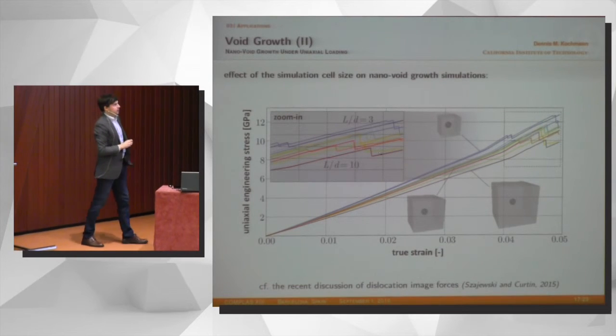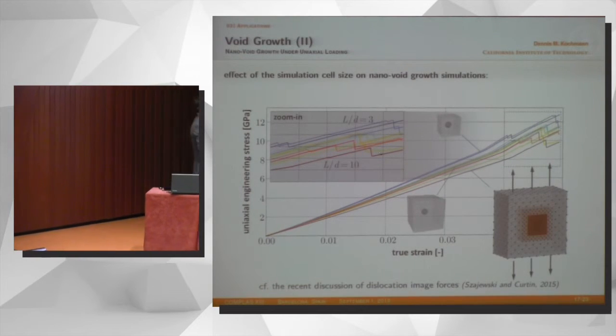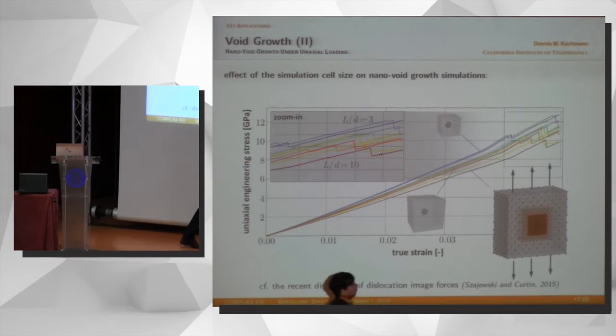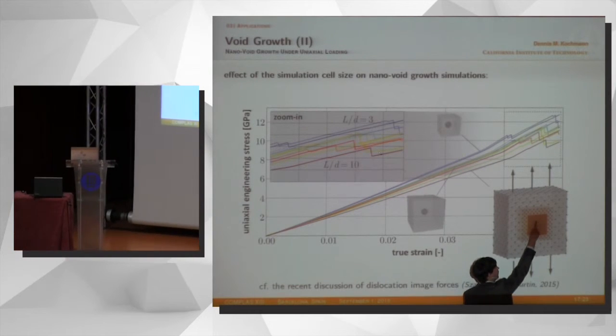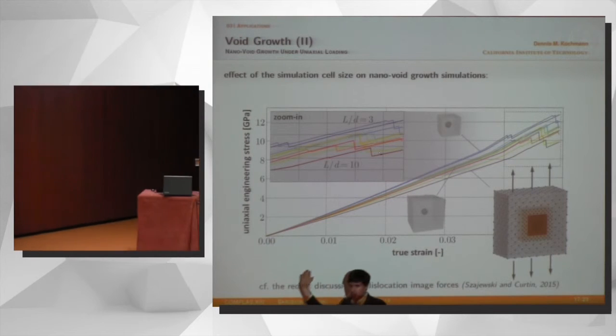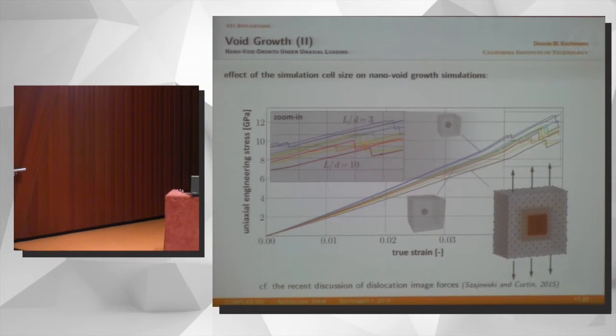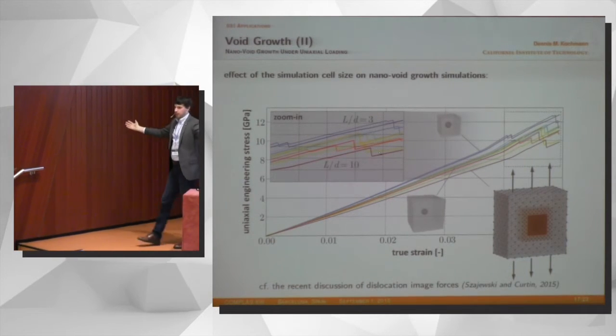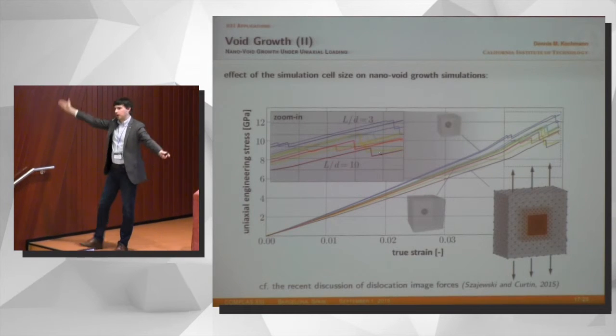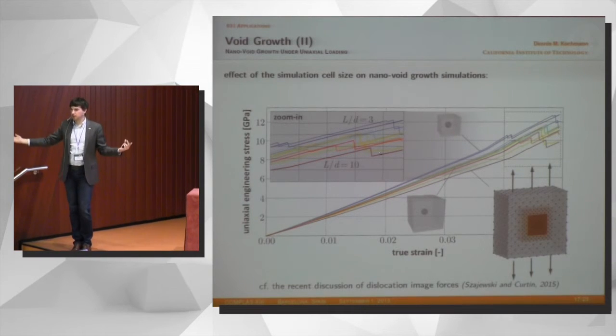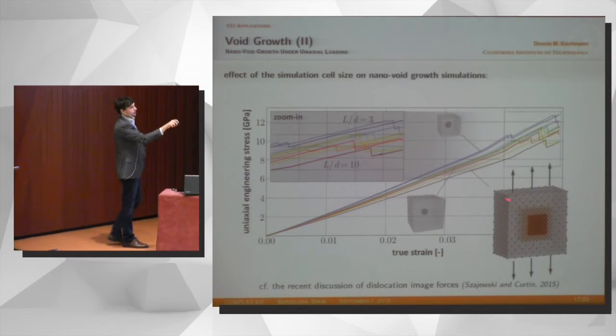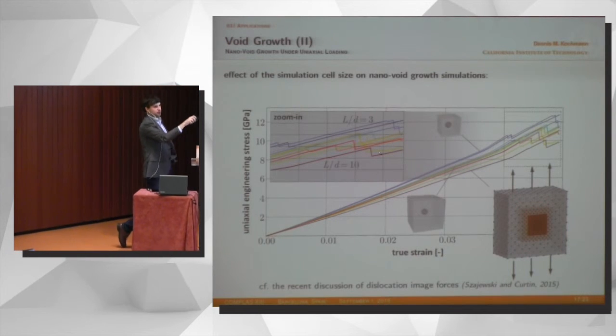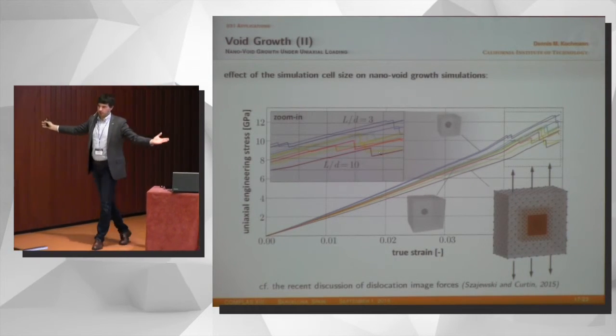The beauty of the QC method that I showed you before is that I don't really have to care about the cell size at all. What I do is I place the void at the center, I have atomistics around it, and then I coarsen them as dramatically as I want. And so by doing this very aggressively, in principle, I could make the cell a kilometer by a kilometer by a kilometer in size. I can still do it on my laptop because I'm simply coarsening. But I don't have to apply boundary conditions right here. I apply them remotely, so they don't matter.